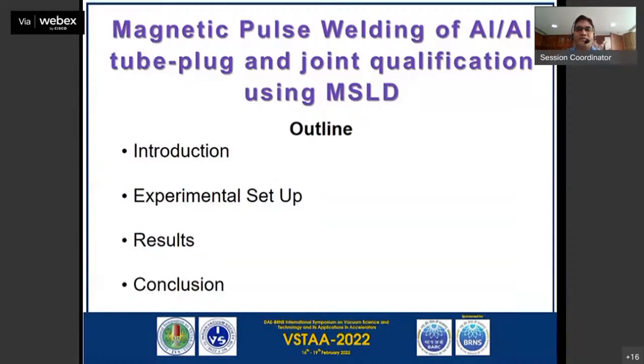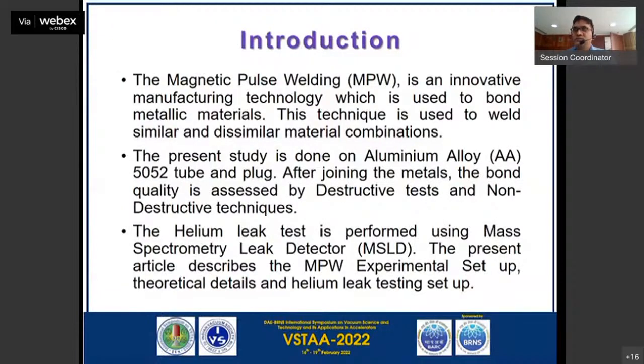The problem with the conventional technique when welding aluminium is due to its high thermal conductivity, more heat energy is required, and the large thermal coefficient of expansion and contraction leads to cracking. Next slide, sir. Here the process can be explained using the Lorentz force. We have to weld two metals. The one metal will be accelerated towards the other metal by using the Lorentz force. So next slide.